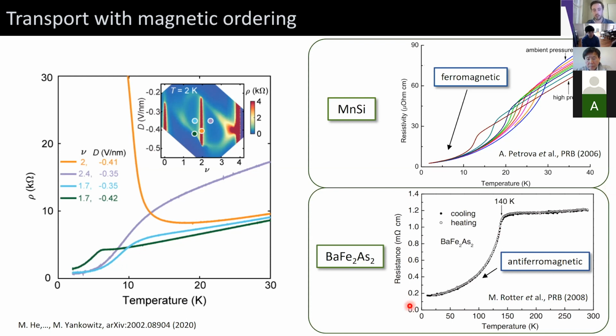And these are thought to arise because there is less scattering in magnetically ordered states. So we don't have a good probe of whether this is the precise mechanism. It may also be related to different phonon scattering modes within these symmetry broken bands, but at least there are some qualitative similarities between these. All right, and the last thing that I want to show you in this system is